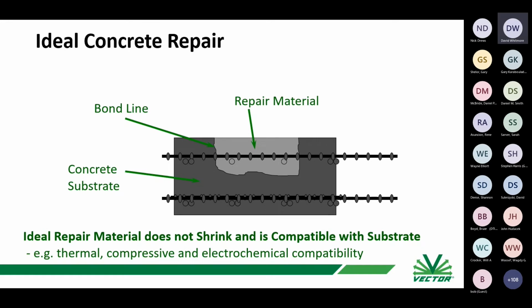And we want that repair to be compatible with the substrate. When we say compatible, we want it to be able to move with and work with the concrete in all ways, both physically, like in terms of modulus. We want the stiffness of that repair material to be similar to the concrete, so when you load and unload the structure, we don't get the load being preferentially put into either the repair or the substrate. We want the thermal expansion coefficient of that repair material to be similar, so that when it heats up in the summertime, the concrete and the repair expand similarly and contract similarly in the winter. That's the reason why most polymer, like epoxy mortar repairs that have been done in exterior environments fail, because you have a big difference in thermal expansion coefficient.